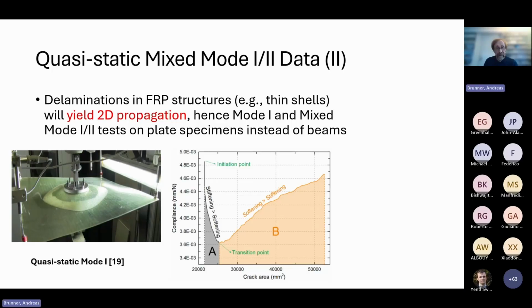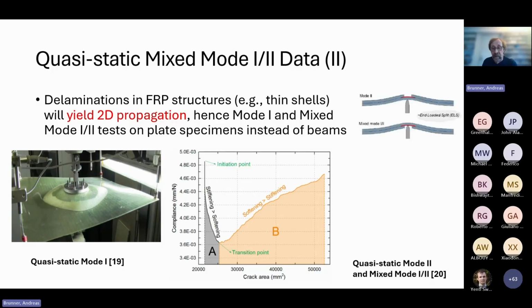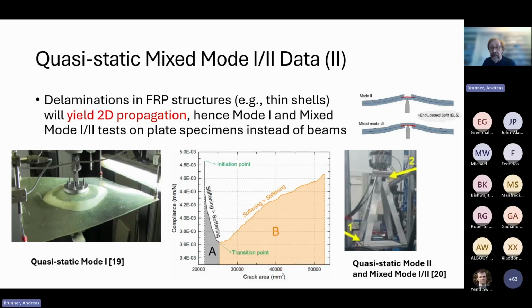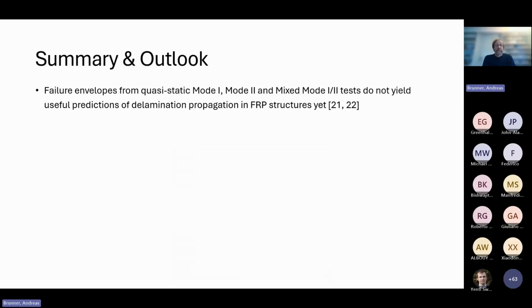And the same methodology, and this was done at TU Delft, has been applied to a mode 2 test or a mixed mode 1-2. And this is the test setup and the schematic of it. And of course, you could probably think of tests, and John Allen has shown an example, where you could also involve mode 3 in these tests. But of course, these are more complex specimens and more complex test setups than what you need for the standard beam specimens.